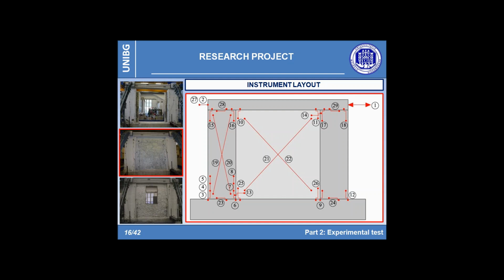The displacement, crack openings, and other kinematic quantities have been recorded during the test by means of potentiometric transducers according to the layout shown in the figure. In particular, the devices located at the interface between the shear walls and foundation, and between the structural walls and the upper beam, have permitted to monitor the respective sliding, giving important information also for the numerical modeling.